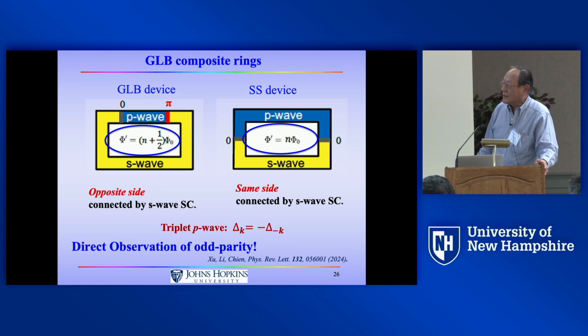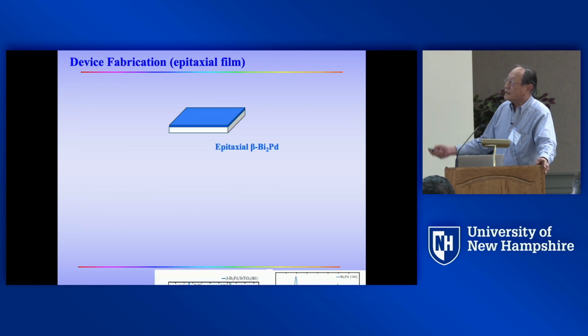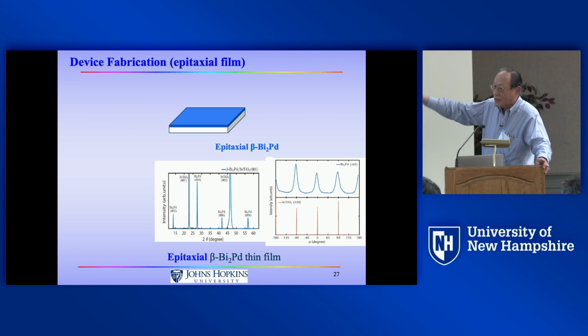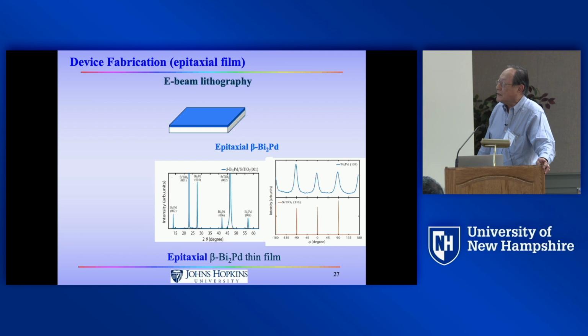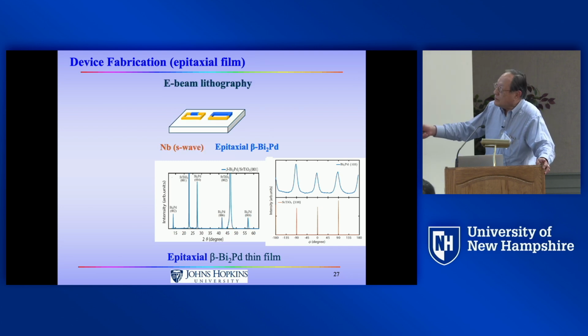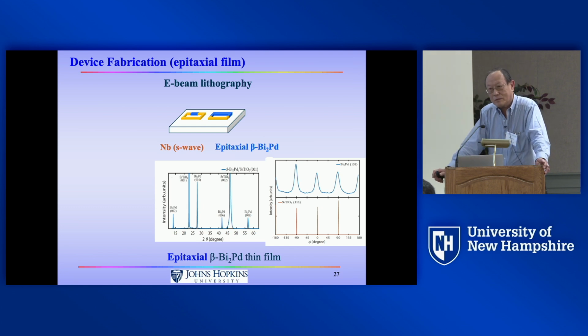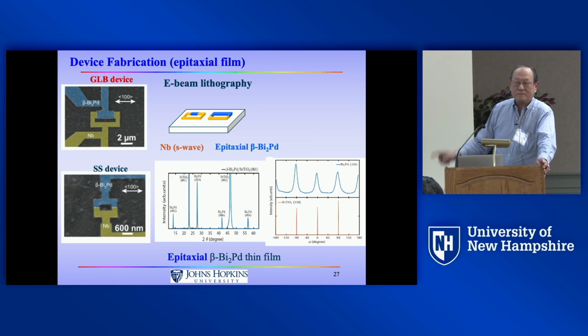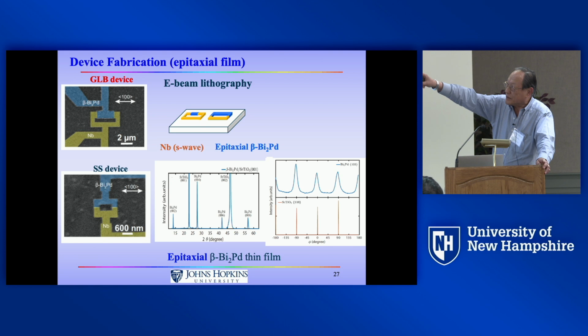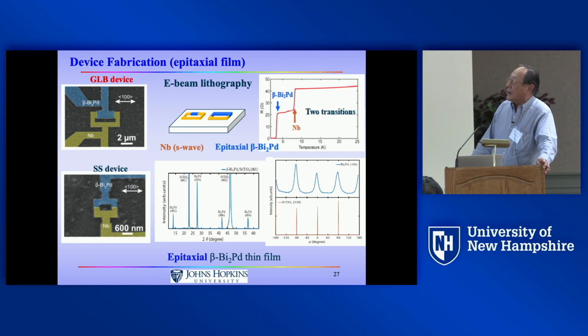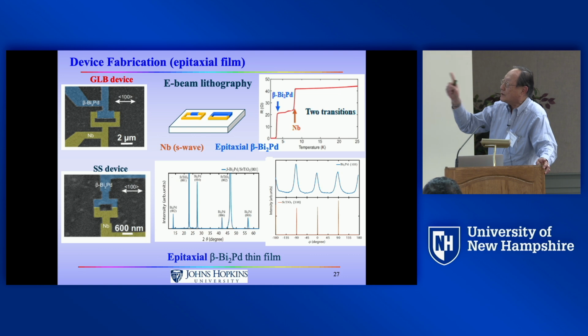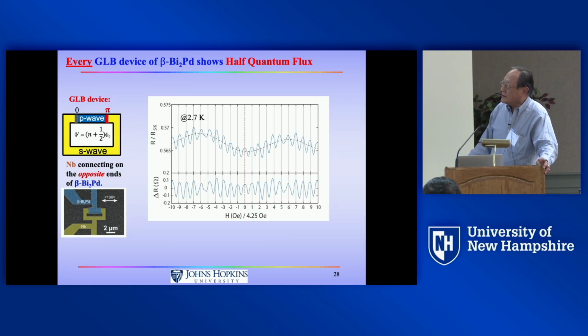So direct observation of odd-parity with only 1 measurement. This is what experimenters need to do. You first made an epitaxial bismuth palladium, then you etch to this thing. Then you make a niobium connecting the other. My postdoc and I both knew how to do this. So he tried it, failed. I tried it, failed. Another person tried it, made it. So it's made. On the left is the GLB composite ring. The bottom is on the same side. And so you know it's connected because if you measure, there are 2 transitions in the same ring because there are 2 superconductors, 1 niobium, 1 bismuth palladium. So you measure this, it is half flux. 1 measurement is already half flux.